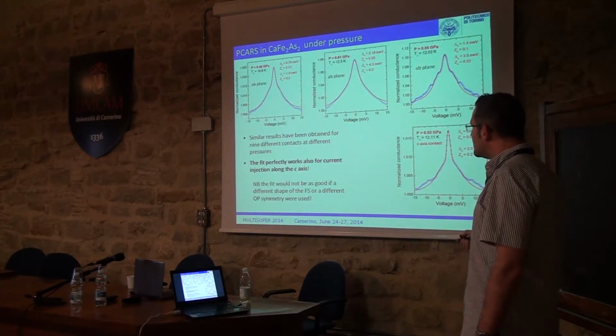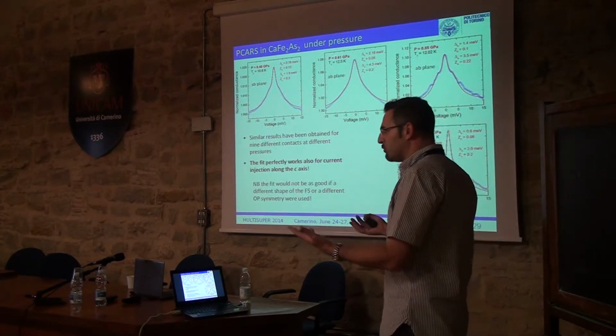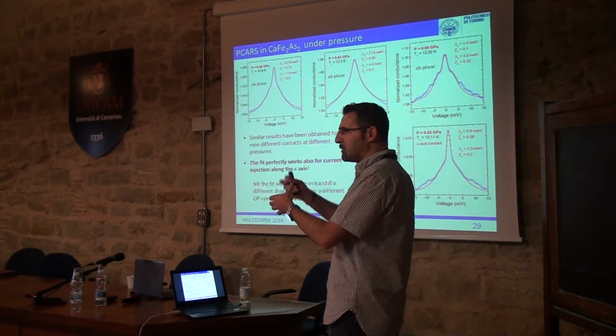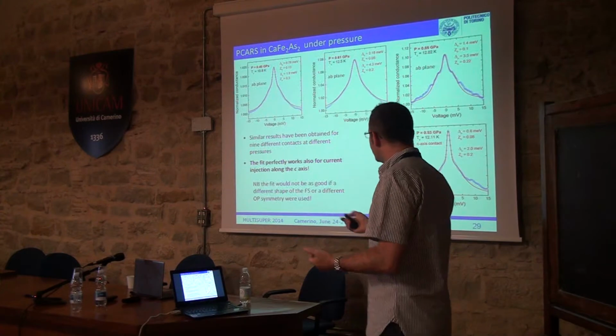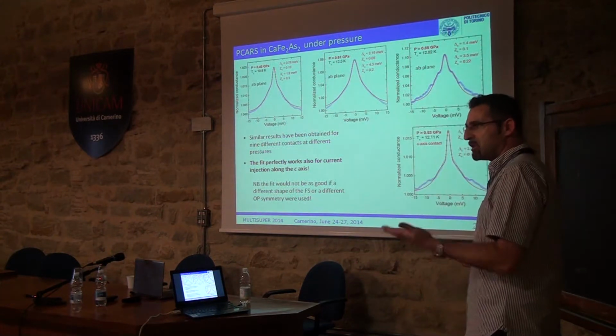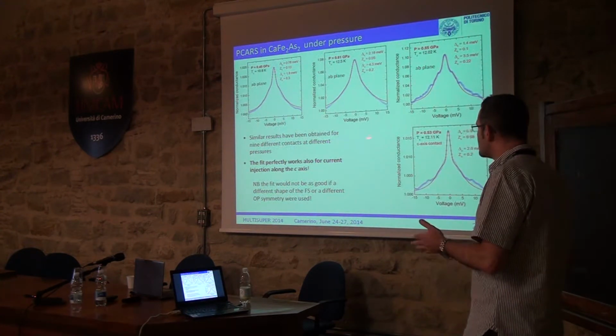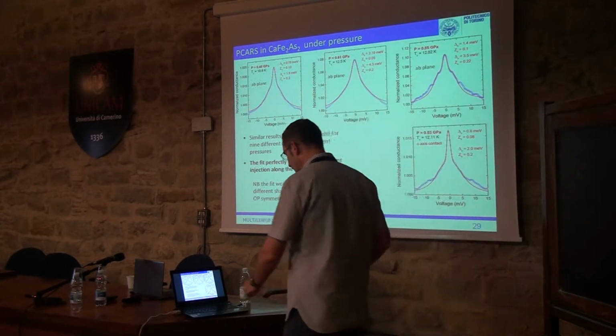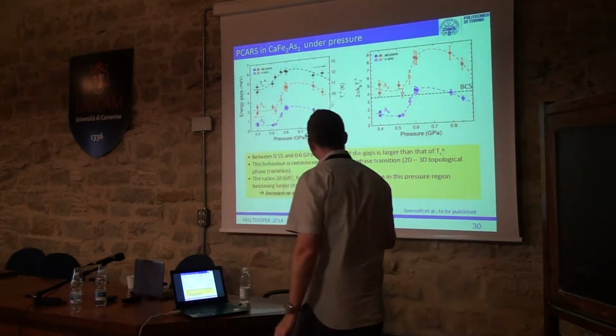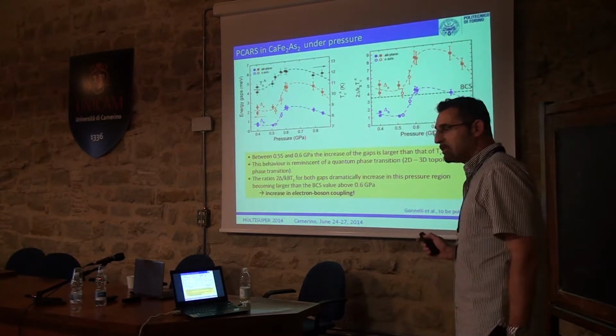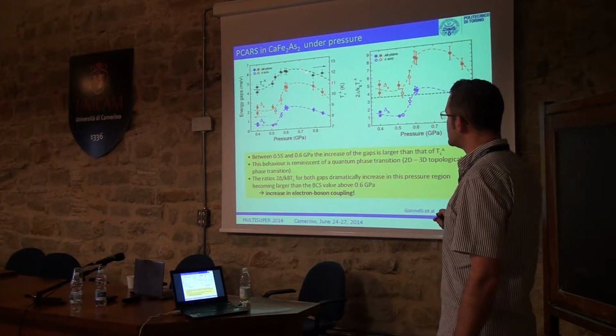Note that with the fit, we have tried to change a little bit the shape of the Fermi surface, the position of the nodes, and so on. And this configuration, which corresponds to the one found by calculation, is the one that allows the best fit. So in the end, I can report the values of the gap amplitudes as a function of the pressure. You see, this is PC.